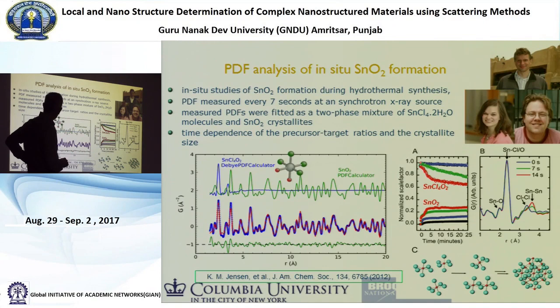So you can see these are the signals from the blue, and then the rest is the green. And what we can do is follow the synthesis as a function of time, and we see how the reagents decrease in time and how the products increase in time, like this. And then you can extract reaction kinetics out.